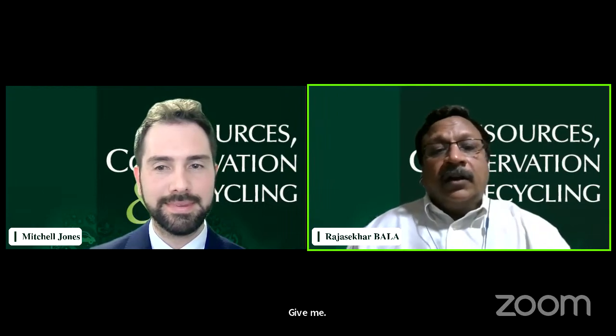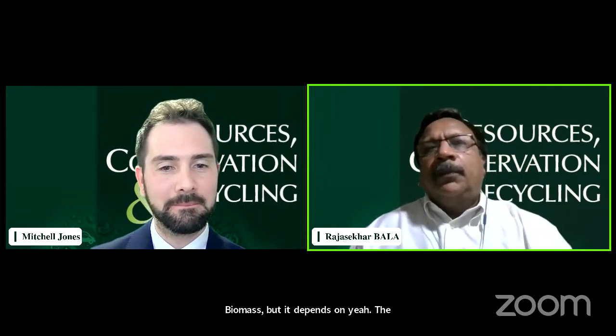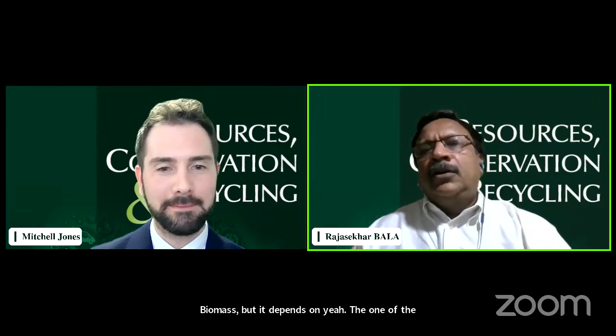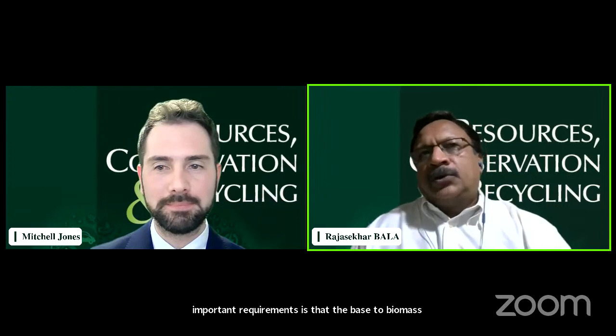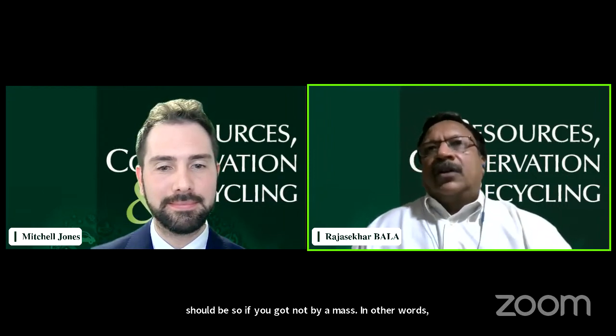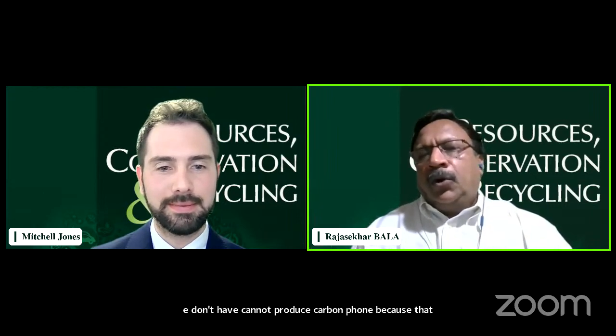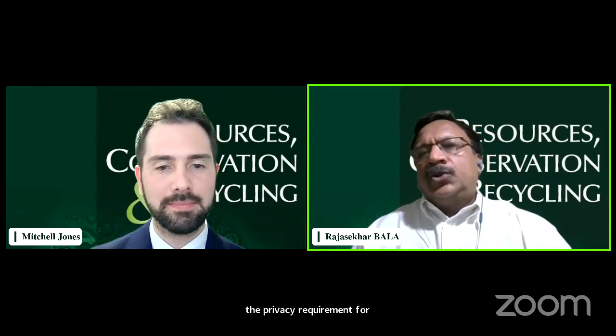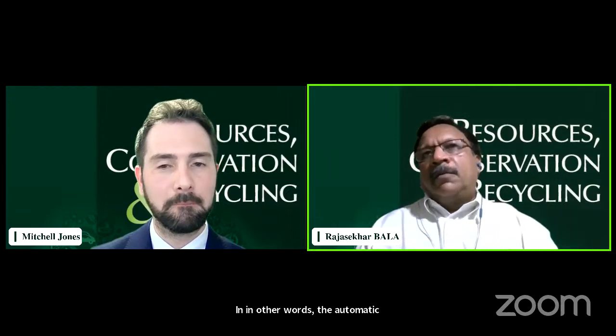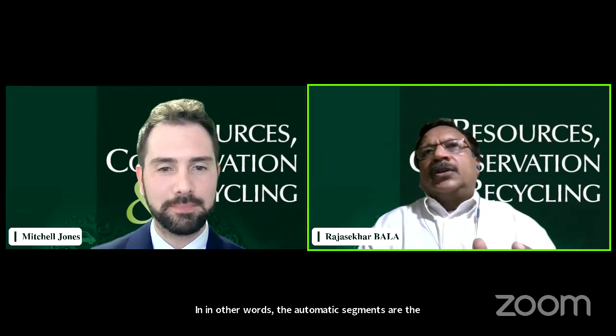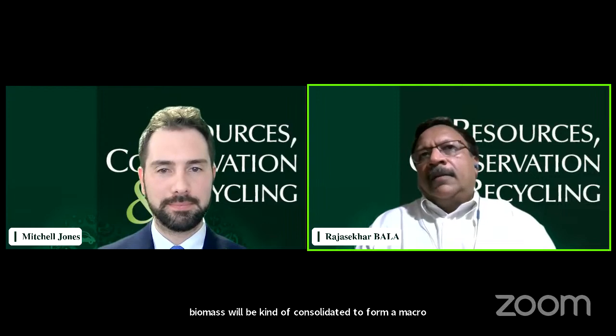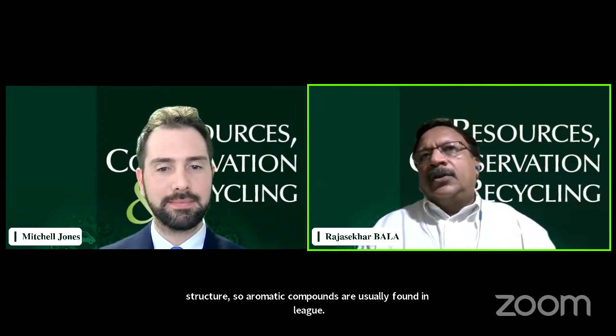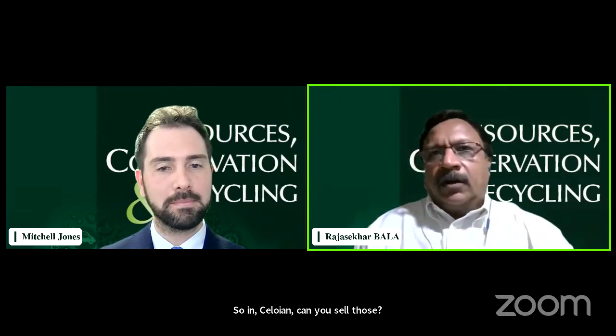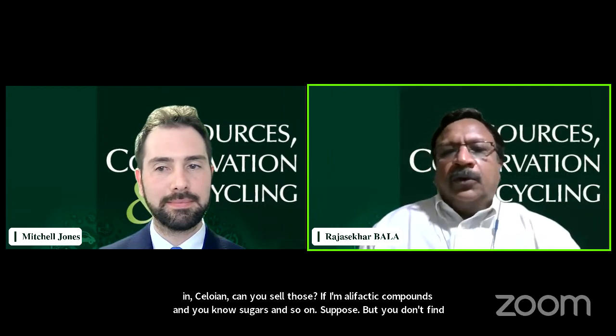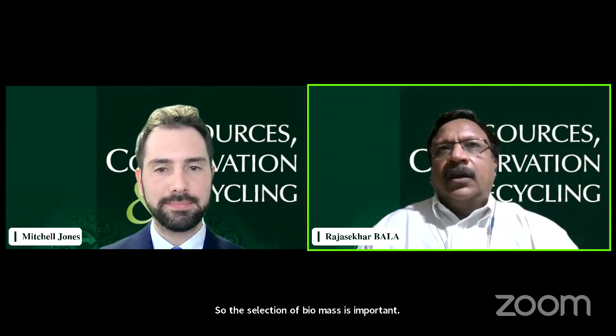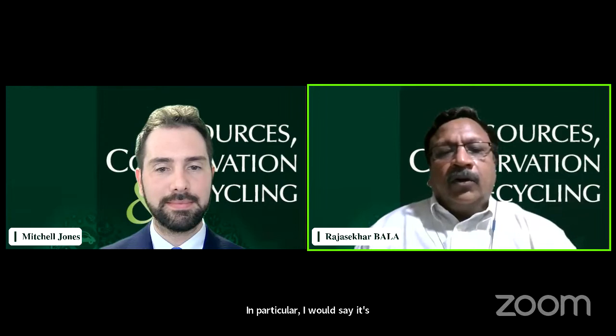Okay, and the next question is what type of agricultural biomass? One of the important requirements is that the waste biomass should be lignocellulosic biomass. If you have non-lignocellulosic biomass, in other words, without lignin, it cannot produce carbon foam, because the primary requirement for carbon foam to be formed is aromatization. In other words, the aromatic segments of the biomass will be consolidated to form a macro structure. Aromatic compounds are usually found in lignin. In cellulose and hemicellulose, you find aliphatic compounds and sugars, sucrose and so on, but you don't find a lot of aromatic compounds. So the selection of biomass is important. In particular, lignocellulosic biomass is an important requirement.